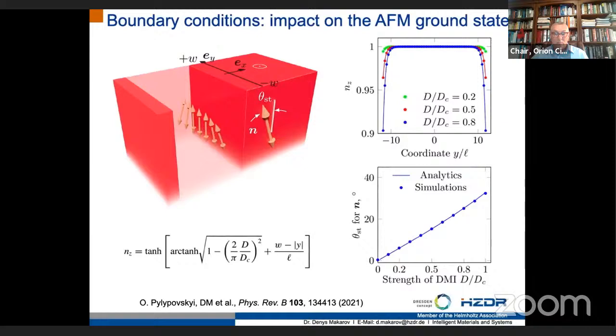As soon as the Néel vector is approaching the boundary, it acquires a tilt, and this tilt can be substantial. It depends on the strength of the Dzyaloshinskii-Moriya interaction and can reach 10 or 20 degrees even for a realistic strength of the Dzyaloshinskii-Moriya interaction constant. It's a sizable effect which should be observable in experiments.